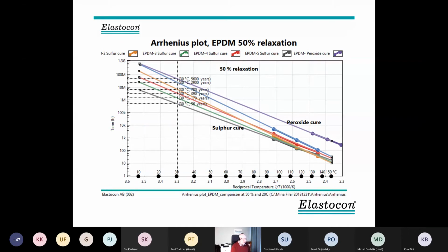So this is a project we made together with Trelleborg. I can mention their name because they have published some of these results. And that is samples taken from all kinds of manufacturers. I don't know more than the polymer type. And we can see we get quite a spread in lifetime estimations from 56 years to 5,600 years at 30 Celsius.